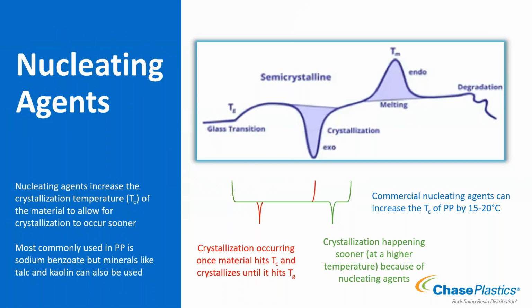And so if we can set it up sooner or increase your TC so it starts at a sooner time, it allows more of a range and more time within those two temperatures to allow for crystallization. And so that's kind of the function of your nucleating agent. A common one for propylene is sodium benzoate, and you can also use other stuff. You can use minerals like your talcs, your colorants. They tend to have a nucleating effect on the material. But standard commercial nucleating agents can move the TC up anywhere from 15 to 20 degrees Celsius. That's common. So instead of starting at like 109 degrees C, which is common for propylene, it might jump up to close to 130 degrees C. So as it's cooling down, it hits that 130 C, and then all the way down to its TG, it continues to crystallize.